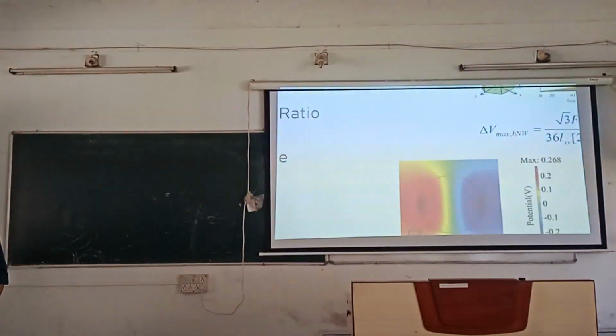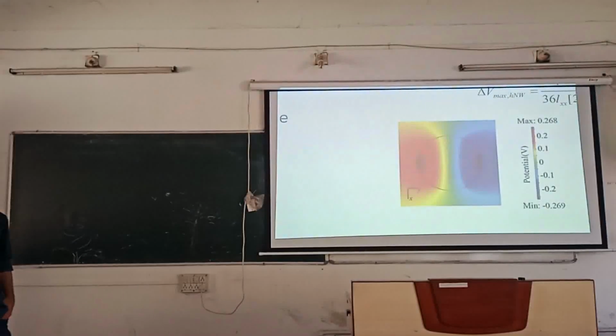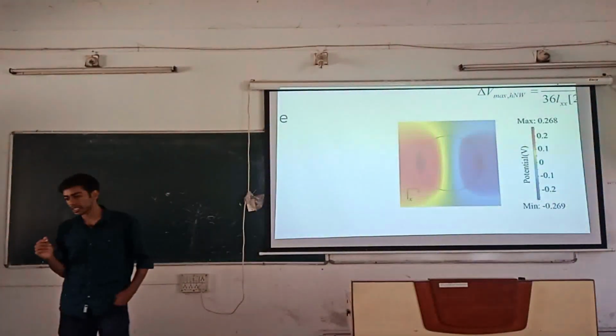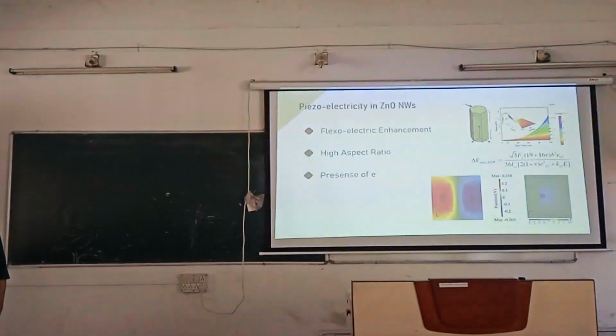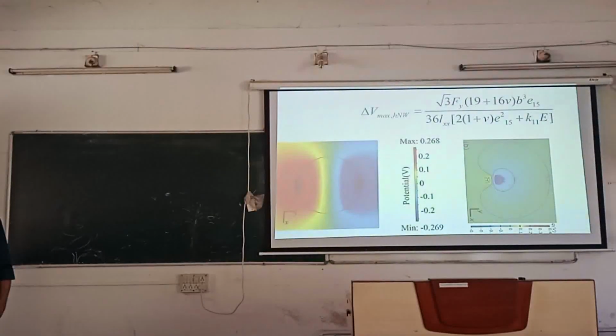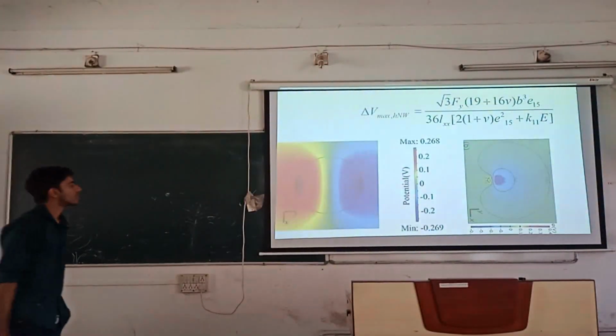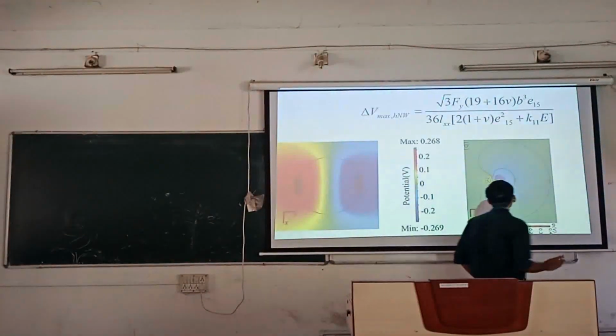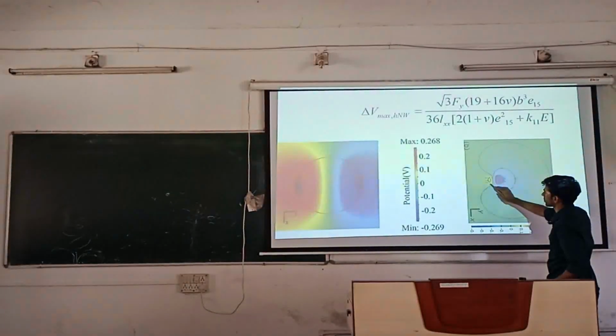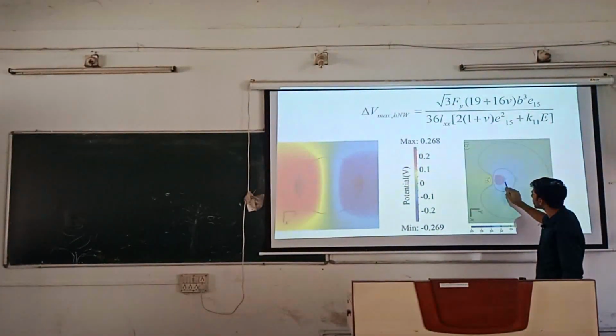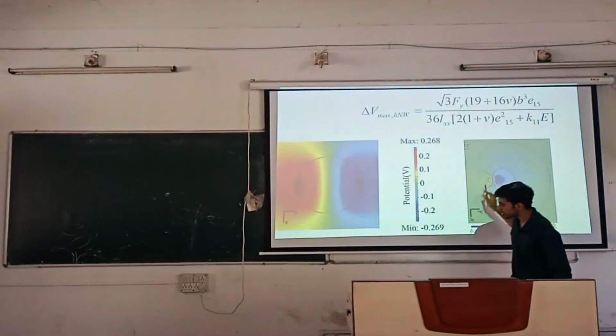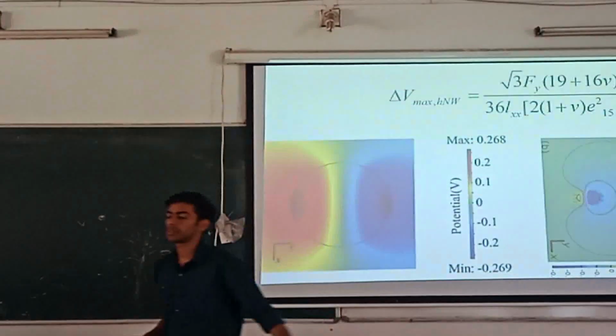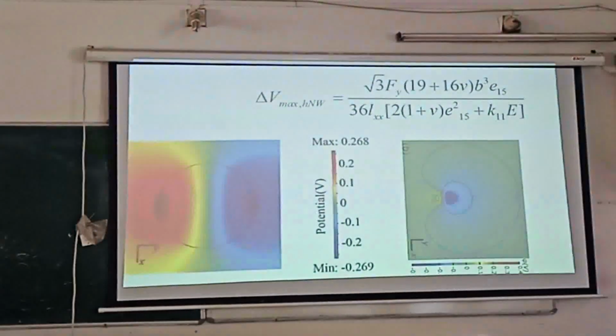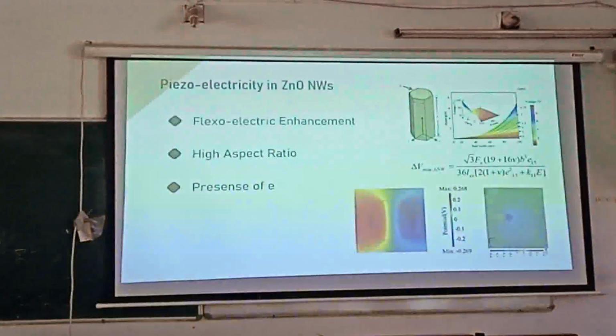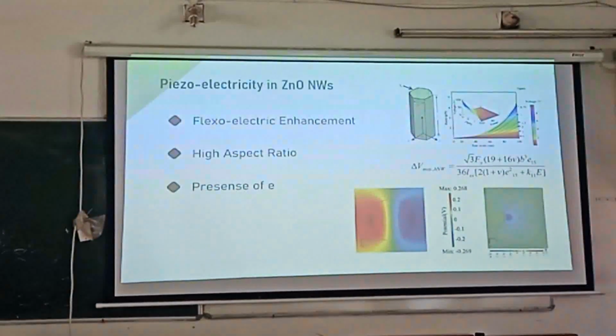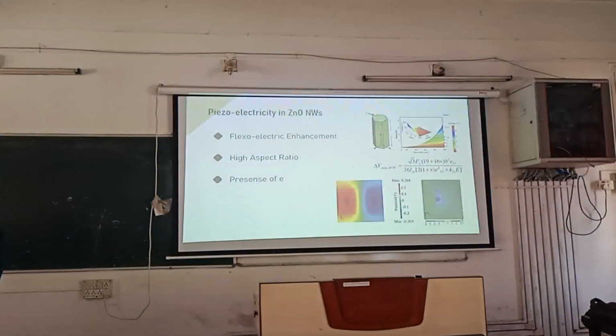So this is what they theoretically calculated. Left side will be plus and right side will be minus. That is what we were expecting. But in practice, we got something like this. From here to here is the nanowire. At the negative side we are getting nearly 0.2 volts, but on the positive side we are getting nearly 0.03 volt. That reduction in potential is because of the free electrons. So nanowires are very good at generating piezoelectricity. Our only problem is we need to get rid of these free electrons somehow.